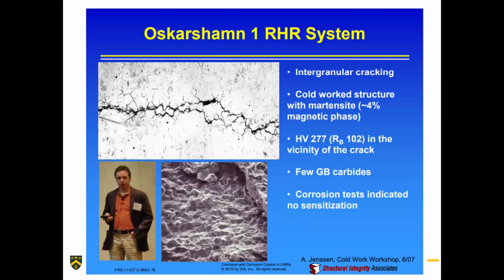So intergranular cracking occurred, believe it or not, surprise, surprise. And the cold work structure with martensite had about 4% magnetic phase, so you can actually measure for that somewhat. In the vicinity of the crack, there were few grain boundary carbides. So this is kind of neat, because you don't have sensitization, few grain boundary carbides, but you've completely destroyed it. That's what I mentioned before about susceptibility. This was a very susceptible material, bound to fail in its current state, but it wasn't sensitized. Great example of that. Corrosion testing indicated no sensitization.